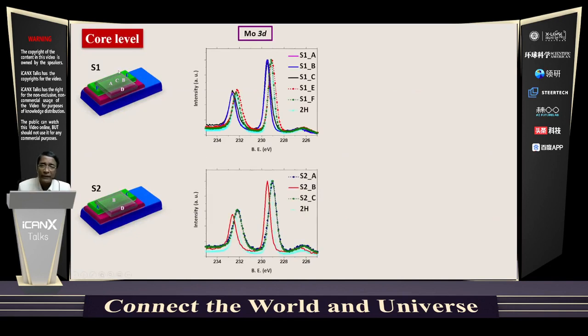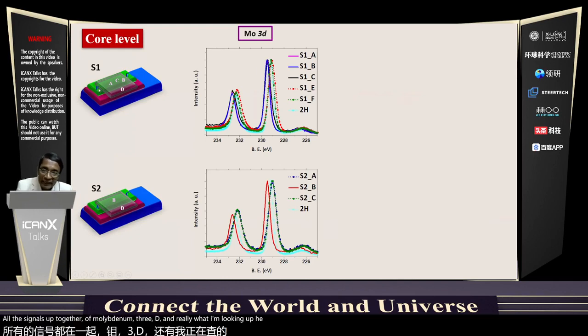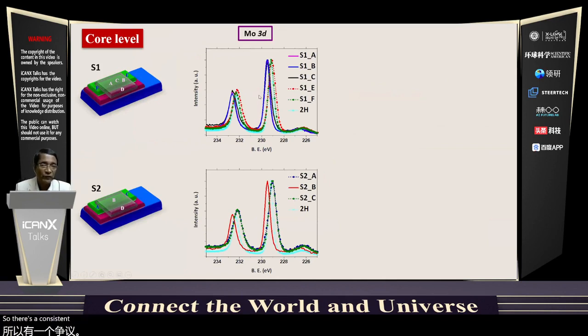When I do that for both the devices, what I find is that A, C, and B are all under the graphene. You see A, C, and B are the solid lines. All the signals are together of molybdenum 3D. And whenever I'm looking at E and F, which is not under graphene, which are those dots, they are shifted. The same molybdenum disulfide. For both the devices that happens. B, which is under the graphene, is shifted to the left, and A and C, which are not under the graphene, are shifted to the right. So there's a consistent shift of the molybdenum 3D.